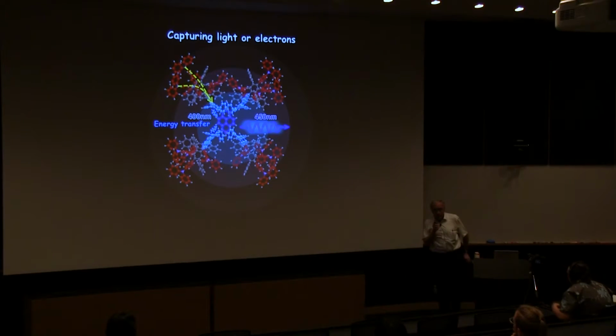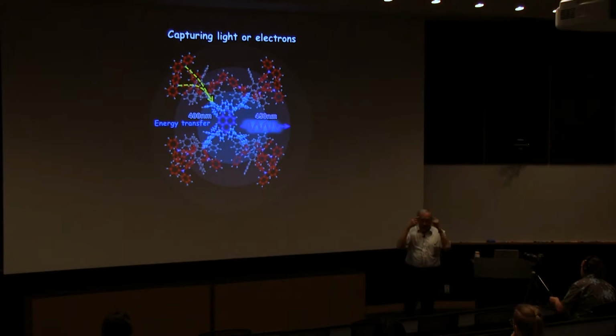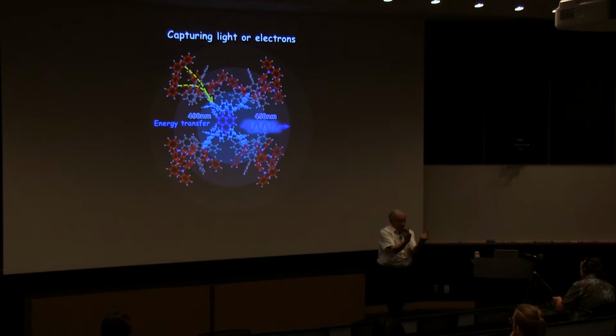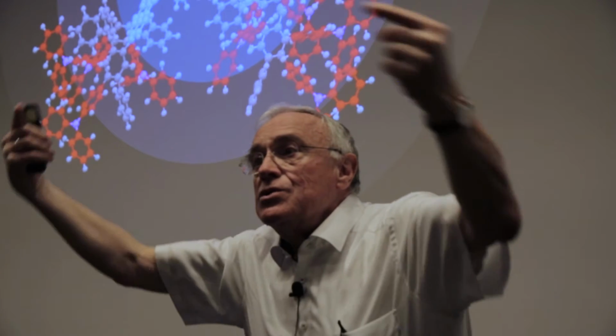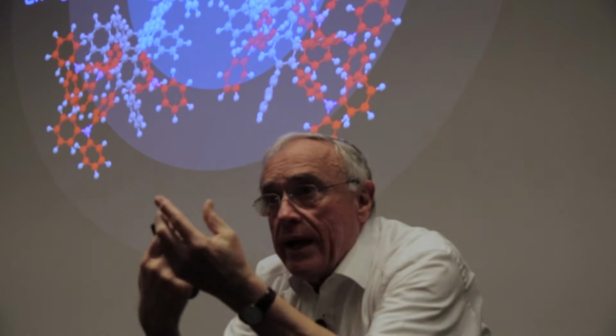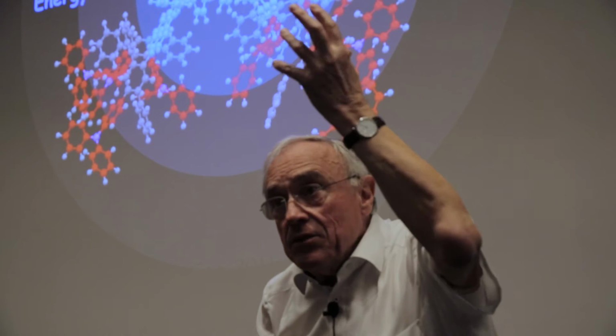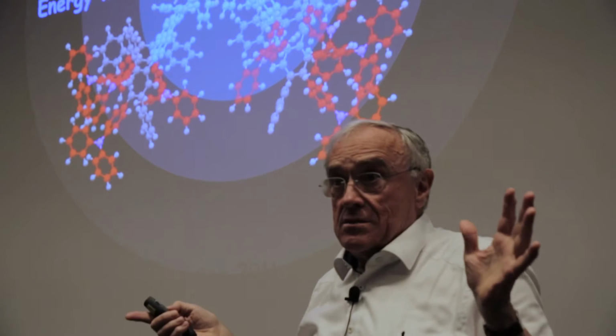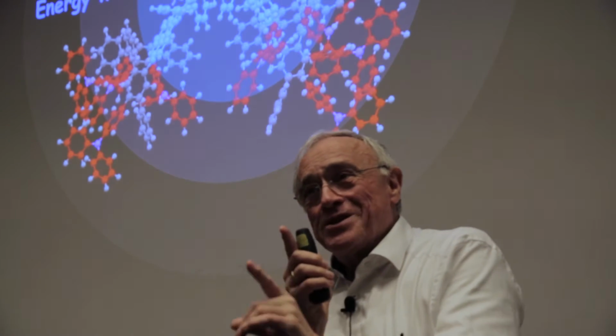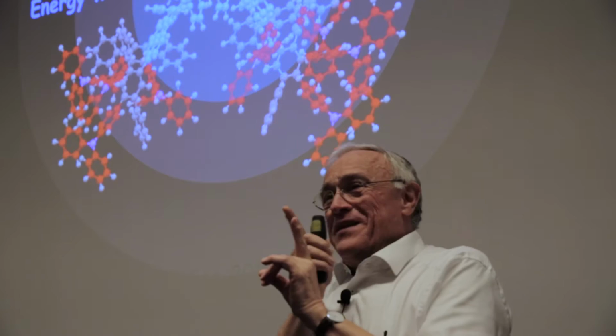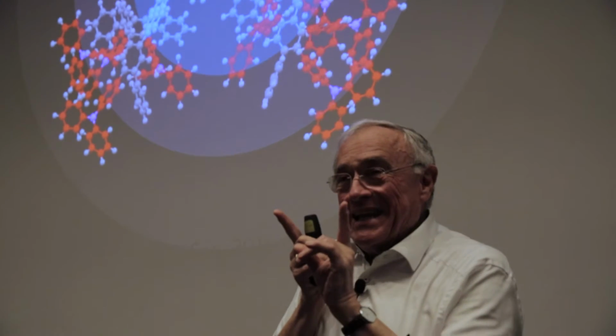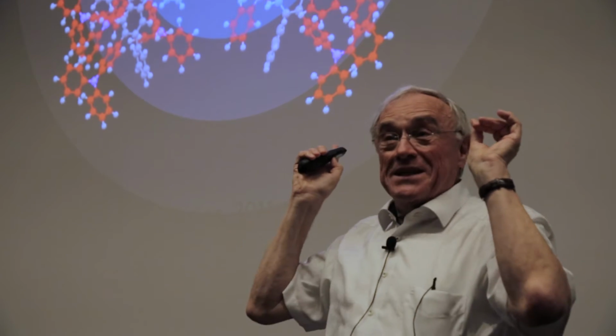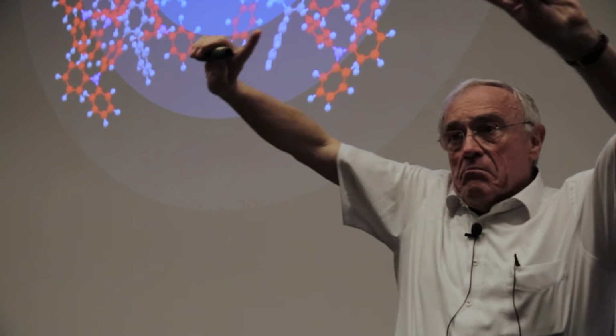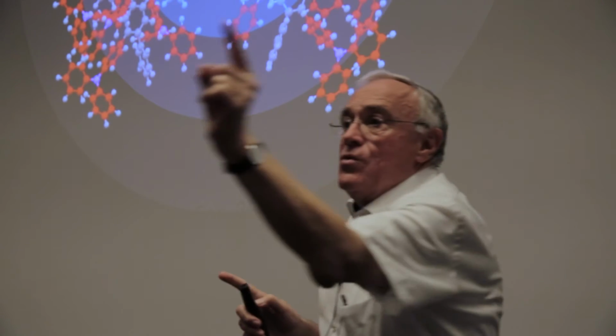This is one problem. Imagine a light-emitting diode, where what happens? You have a positive and negative charge meeting, recombining. So at the same area, you have excitons, excited states, and charges. This is disastrous. And by the way, nature in photosynthesis has a way of removing the charge from the photochemically excited states. This is what we do in a dendrimer: we let the charges combine in that three-dimensional particle, and then we move the excitation energy to the inner core by energy transfer, which is an ultra-fast process.